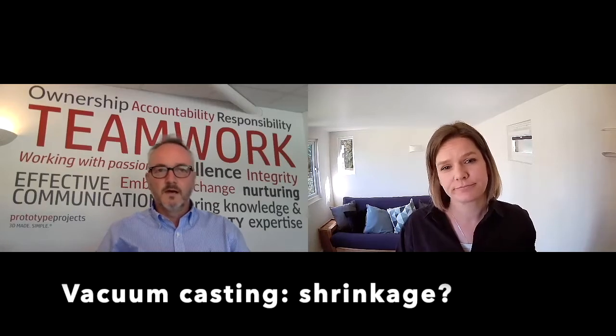Okay. Do you have problems with shrinkage in vacuum casting? So with the process of vacuum casting, you don't generally have shrinkage issues or problems, because the way that the process is worked up, it's all done through heating up the tool and cooling down the tool. So the master models are generally printed 1-to-1. And then when the tool is heated up in the oven prior to casting, the tool expands, the warm resin goes in, the tool is cured off, and then the tool will cool down. So the shrinkage is linear.